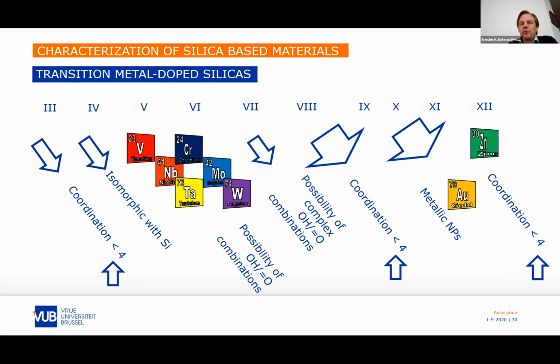So here I wanted to make a kind of overview of what we know on transition metals grafted in the monomeric form, through the periodic table. If we go from group 3 to group 12, the first elements have a lower coordination, as we've seen for zinc, so lower than 4. So we can expect some reorganizations, as we've seen for zinc. Group 4 is isomorphic, which is already known and studied with titanium, which is used in photocatalysis. So we can isomorphically substitute silicon. What we can investigate there is the effect of the substitution on the electronic structure, directly linked to the stability. Is there an upper concentration of the titanium in this structure or not?